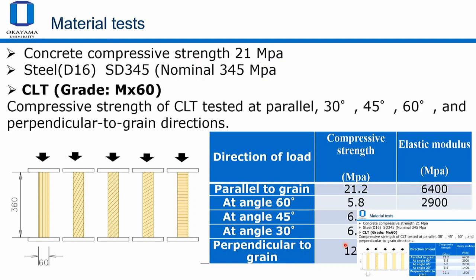Because I'm thinking about a compression strut on an angle, I thought, let's test the compression strength on different angles, cutting the CLT at different angles. What I found is that the weaker direction of CLT is not perpendicular to the grain. It's actually at 45, or between 60 and 45 degrees. It's much weaker than perpendicular to the grain. So the strut direction is actually the weaker direction. For me, that was new because I am not used to working with CLT. I was always thinking that perpendicular to the grain is the weakest.